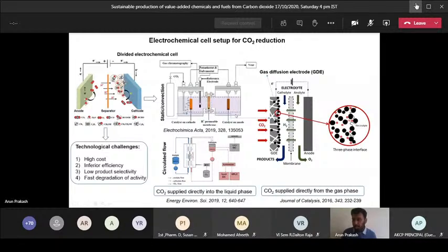So people are trying to use non-aqueous electrolyte without adding any water. Organic solvents can be used as the non-aqueous electrolyte. In organic solvents, CO2 dissolves much better than it dissolves in the aqueous electrolyte. So the main reason is, when you use a non-aqueous electrolyte, you don't have water, so there is no proton source. If there is no proton source, hydrogen will not be produced. So you are able to suppress your hydrogen evolution reaction by using a non-aqueous electrolyte.